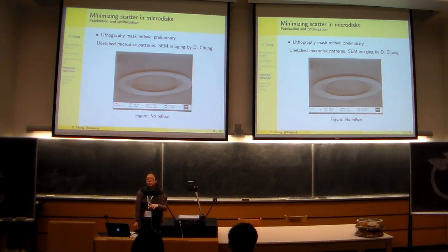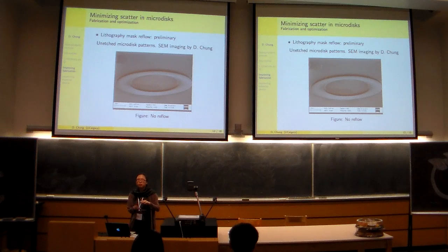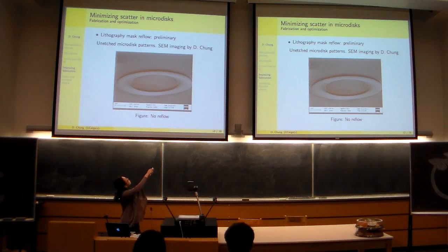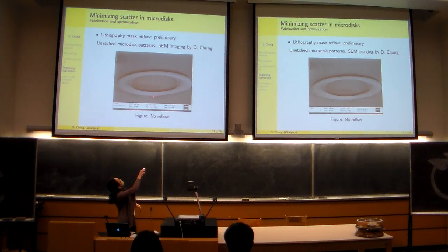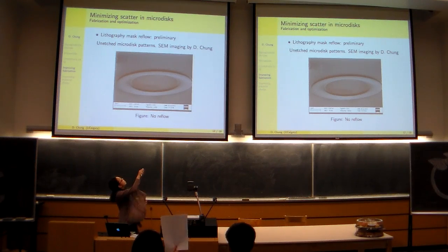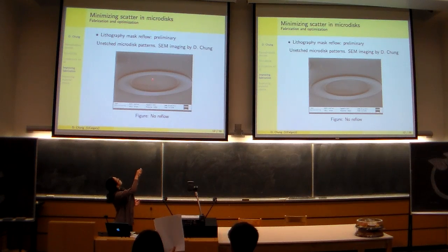So how do I make one of these discs? I pattern the surface of silicon. So I pattern silicon with something called electron beam resist. And I draw one of these circles onto the disc. So this area is exposed silicon. And this area is protected by the resist. So when I go to etch one of my samples, this area will be etched away, and this middle area will be the beginnings of my disc.